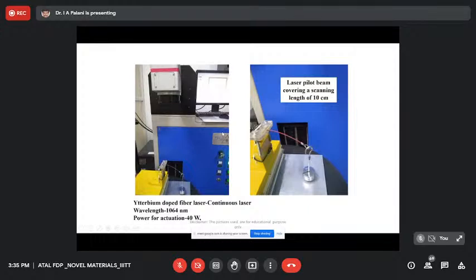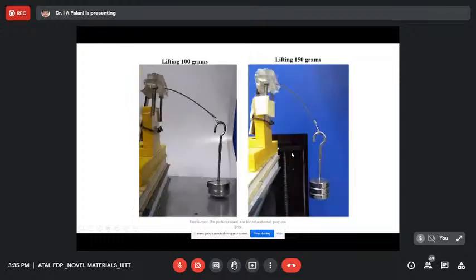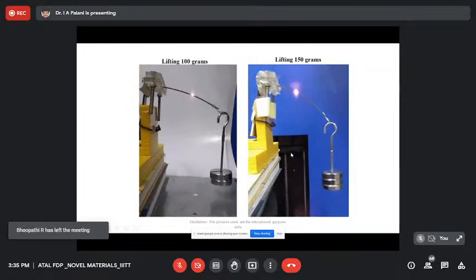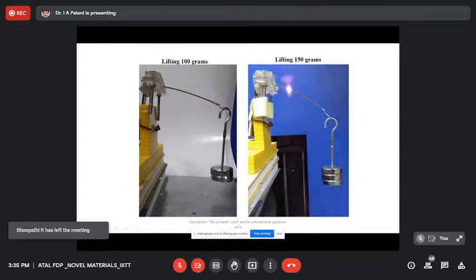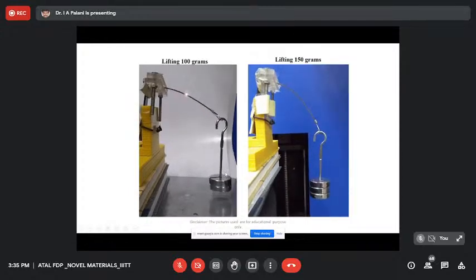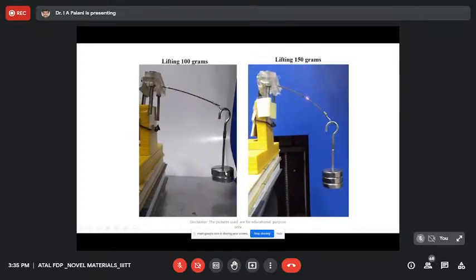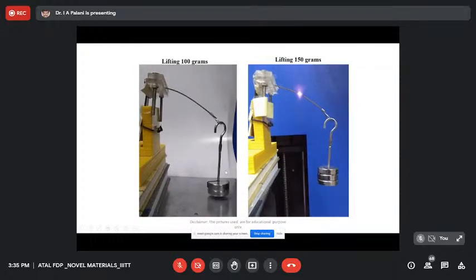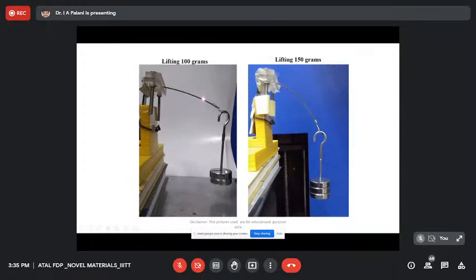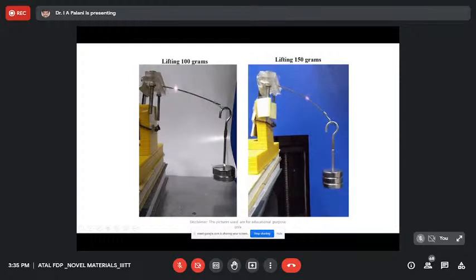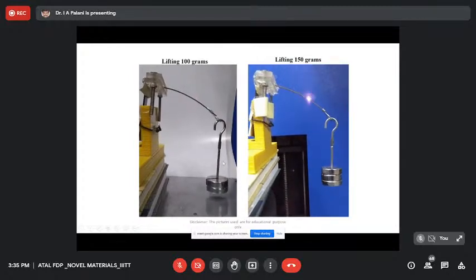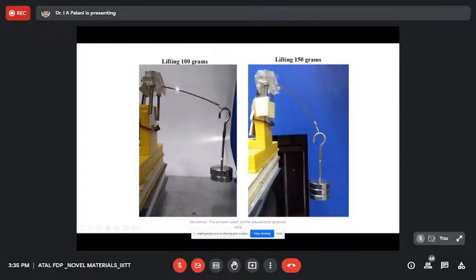So this is a fiber laser which we have used. It's an ytterbium doped fiber laser, and this is a kind of shape memory strip which we have come up with. So we have just tied a weight to it, 100 gram and 150 gram. And the laser is made to irradiate on the strip. And we could see the actuation behavior.